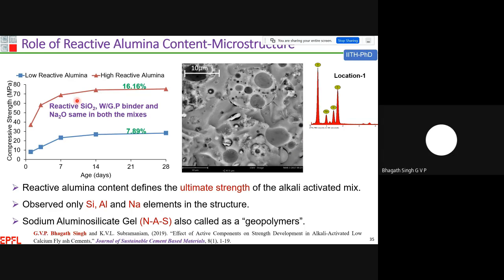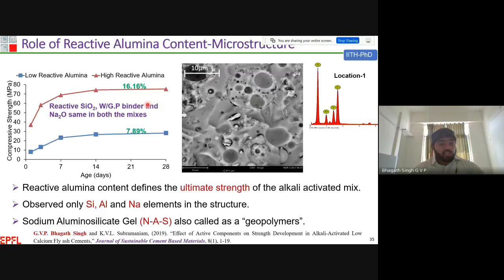and still the research is going on for this particular component. And to understand the role of reactive alumina content in fly ash based mixes, I have used two different source fly ashes. One fly ash is very rich in reactive alumina, about 16%. The other fly ash has reactive alumina of about 8%. In both the mixes, the total reactive silica, the water to binder ratio, and the sodium content are the same. The only variable is the reactive alumina content. Then the ratio is also the same.